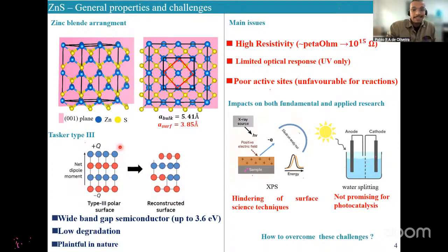And first, these systems are not stable. Actually, to reach equilibrium as a requirement from the thermodynamic point of view, you must compensate this dipole that arises at the surface. And for this, usually this kind of system undergoes some reconstruction. By reconstruction, I mean you usually break the translational symmetry. And this is one of the key points that we're going to explore in one of our works. But I just want to introduce it because it might be important in the next presentation.